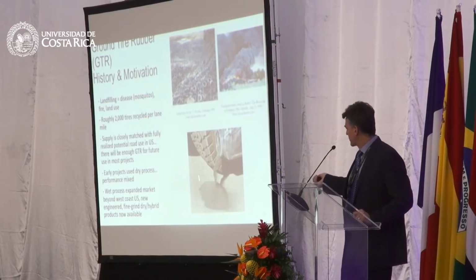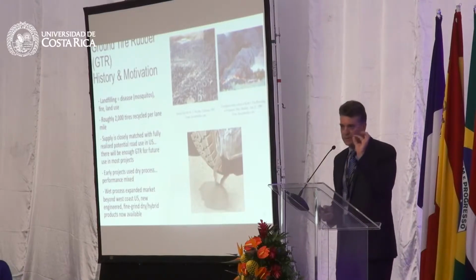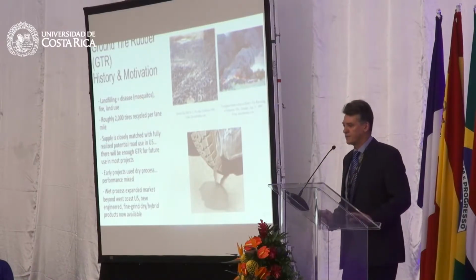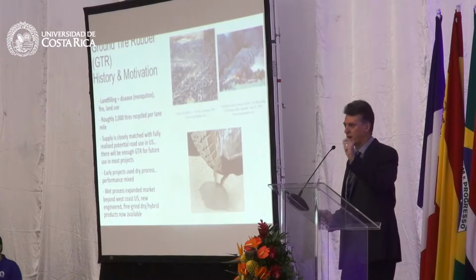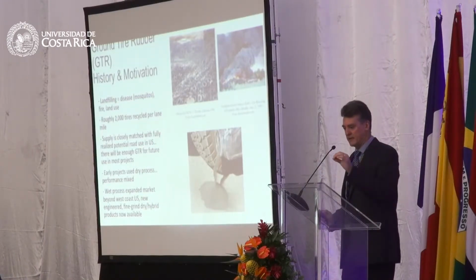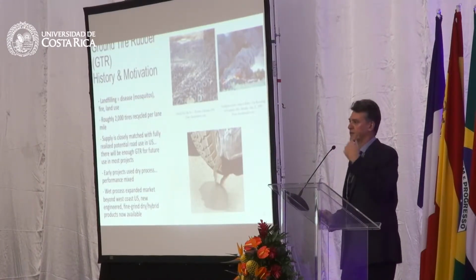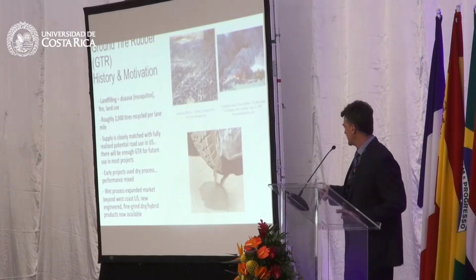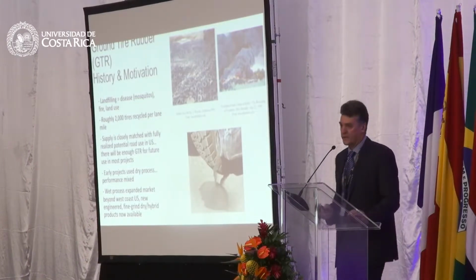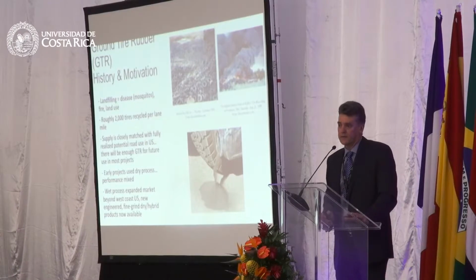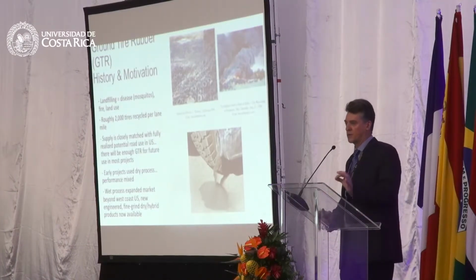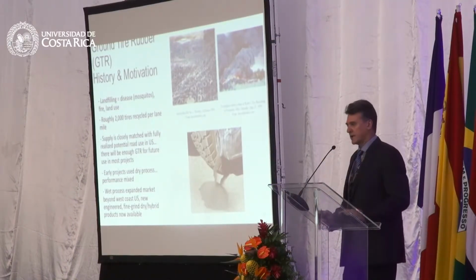What we found recently is ground tire rubber is becoming finer and finer. The manufacturers are finding ways to make the size of the particle very small, maybe fitting through a number 30 sieve or a number 50 sieve. The particle size is getting quite small, and the processes are becoming more sophisticated, so the quality control of these products has improved.